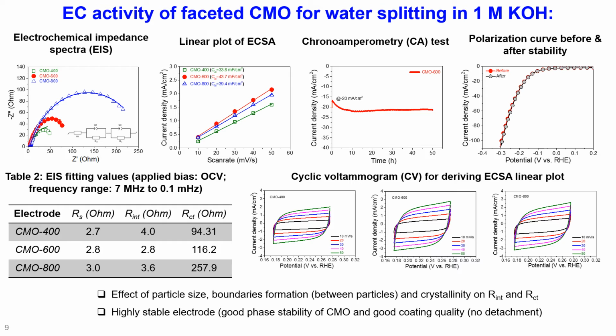And then the CV curves for deriving the ECSA and the linear plot are shown here. From the CV graph, the linear plot of ECSA has been drawn here. So from this, the Cdl of CMO 600 is much higher than the other two electrodes at 43.7 millifarad per centimeter square. The chronoamperometry test, that is the stability test of CMO, has been shown here for 50 hours. So we can see clearly that there is no decrement in the current density even after 50 hours. There is no loss here.